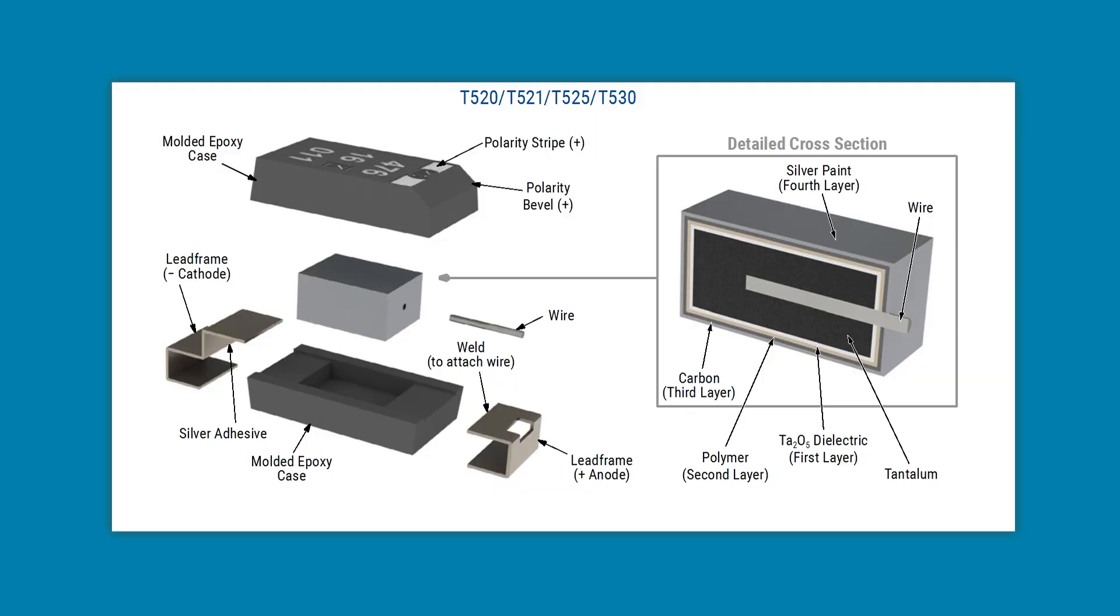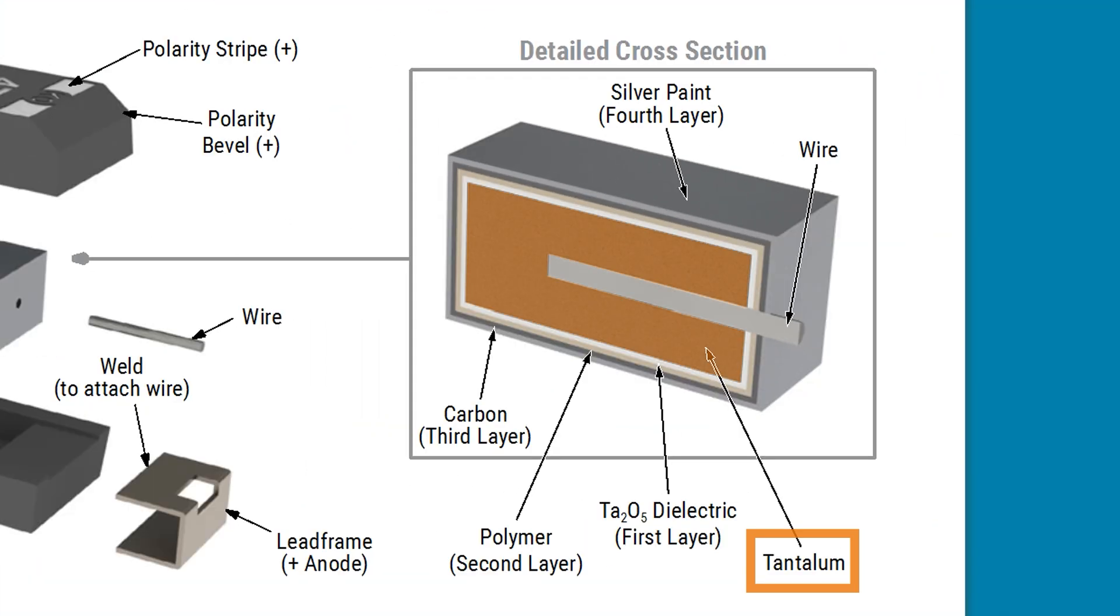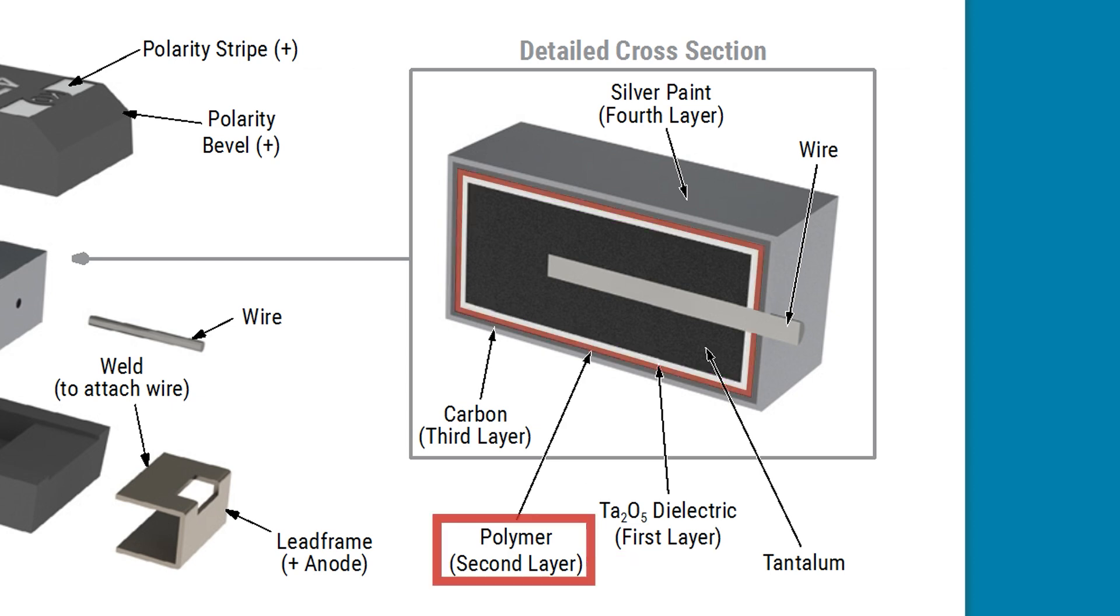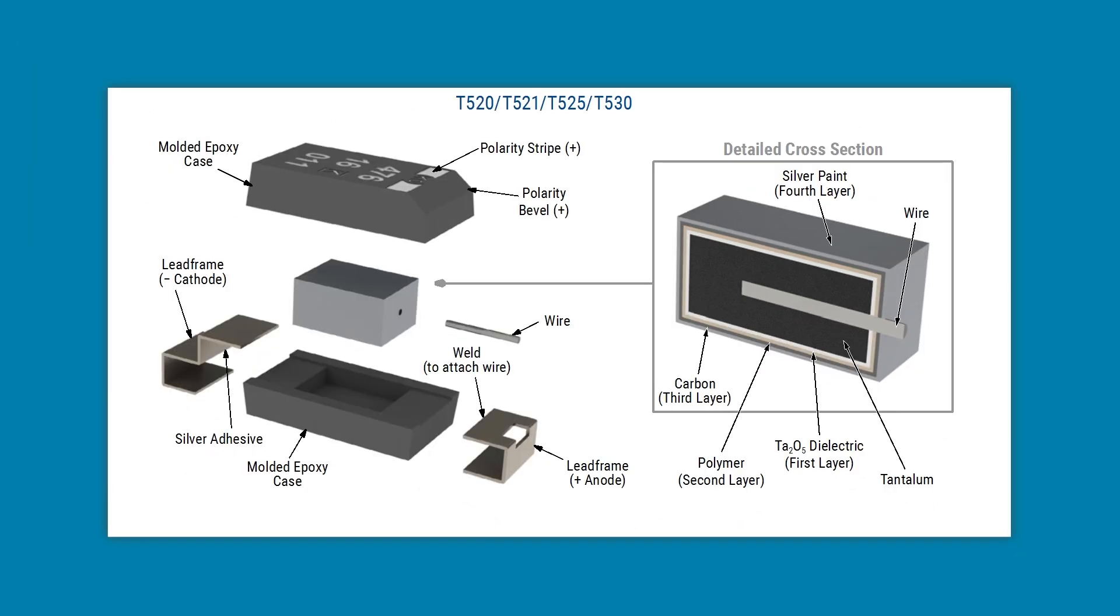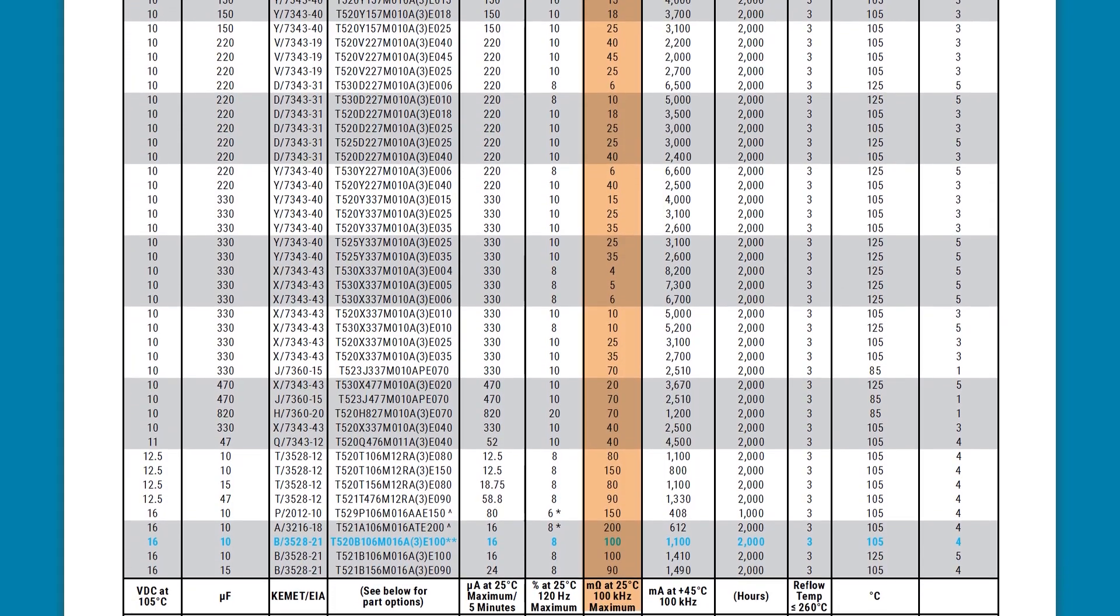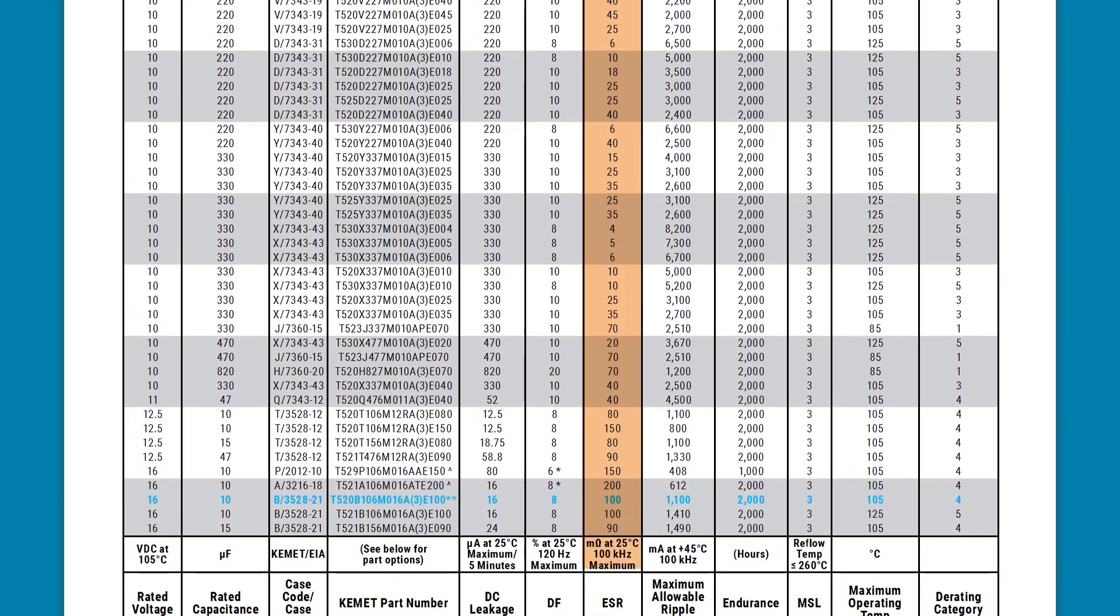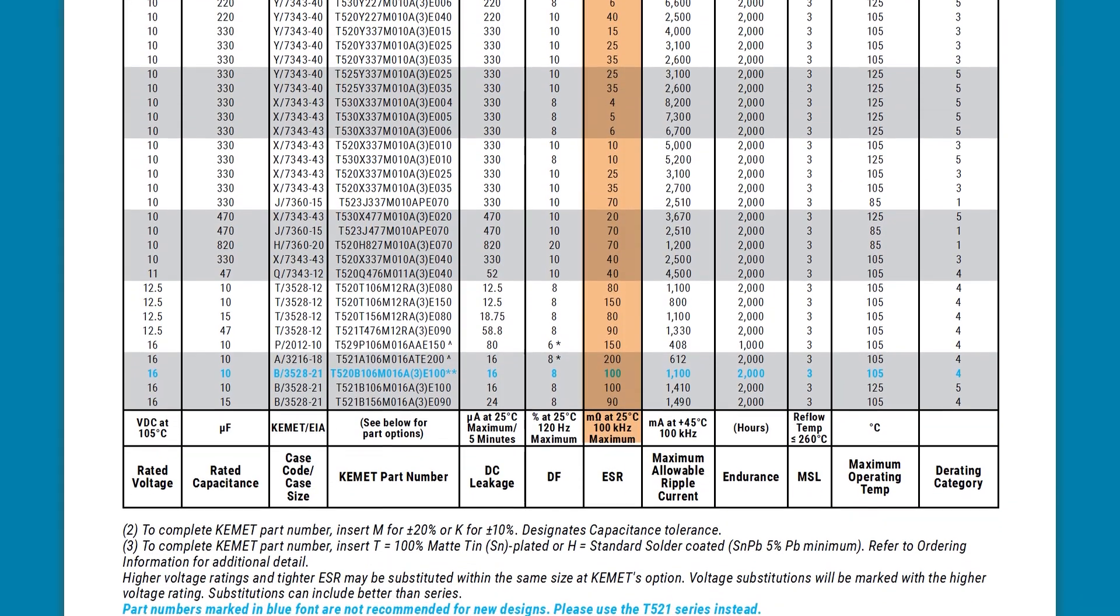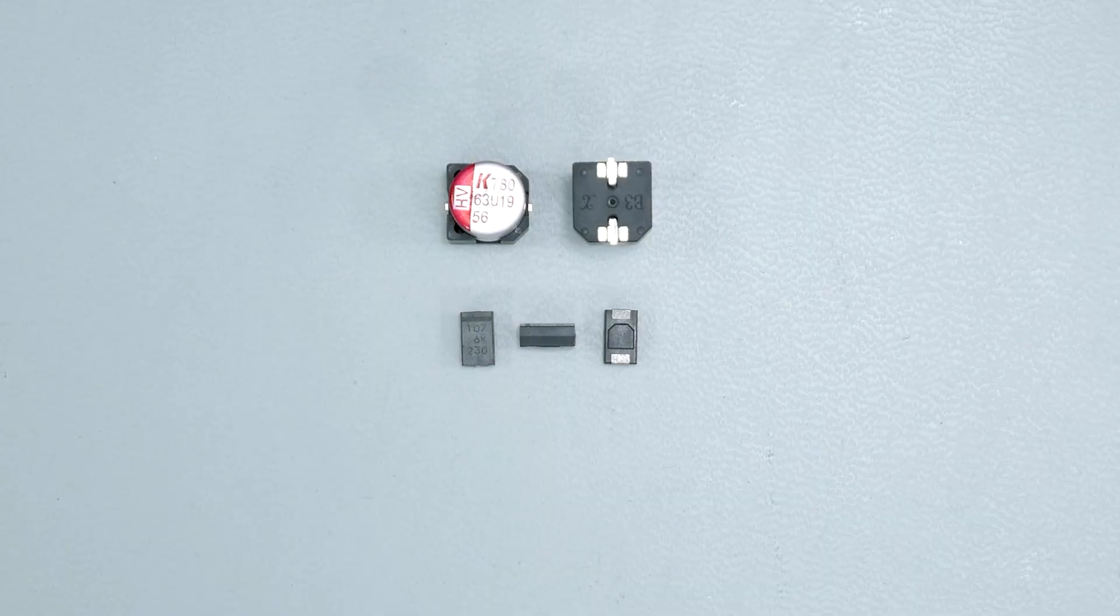Chip-style polymers are electrolytic capacitors made with tantalum as the anode, tantalum pentoxide as the dielectric, and a layer of PEDOT as the cathode. PEDOT is a solid conductive polymer material. These have very high capacitance and relatively low ESR. Most importantly, they do not have a DC bias effect.